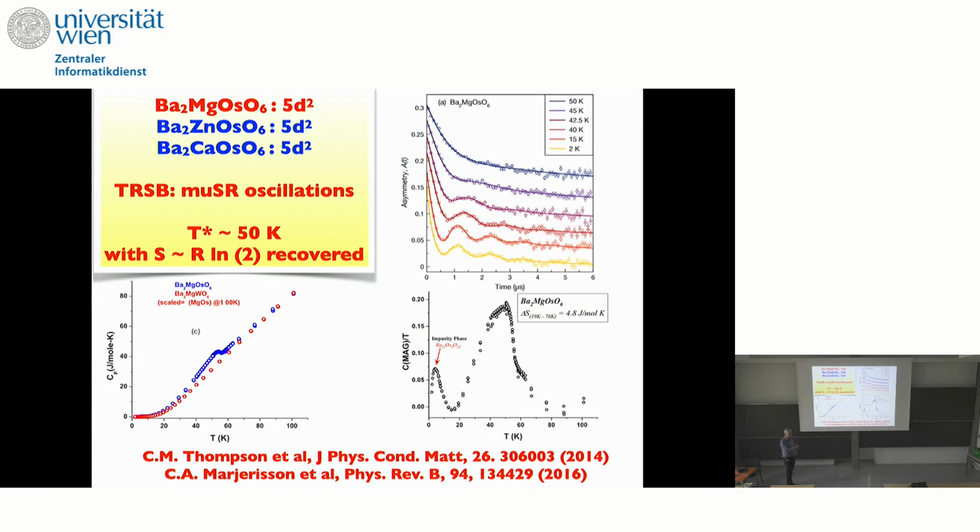And so to do that, you've basically got to integrate up the magnetic heat capacity divided by T as a function of temperature to get the entropy. And that's relatively straightforward to do. You see it done all the time. The only thing I'd like to point out here is that it's not a trivial thing to do when the phase transition of interest is anything above 10 Kelvin. And the reason for that is because the heat capacity is completely dominated by the phonons.